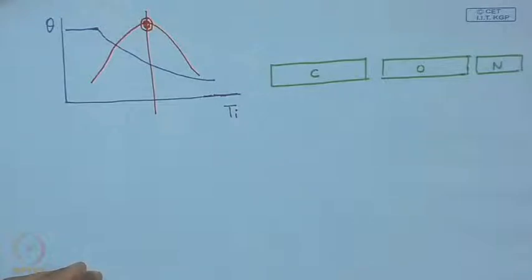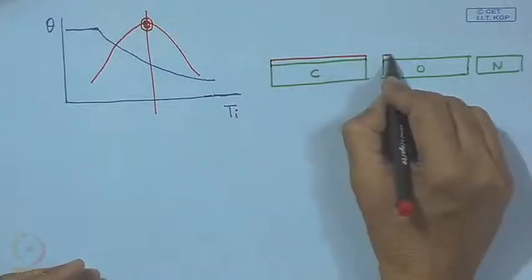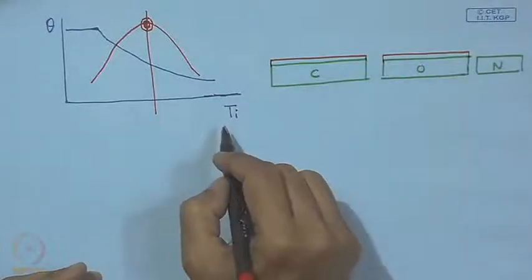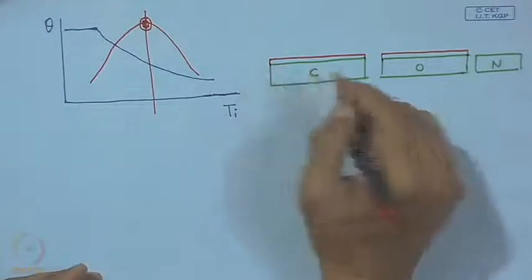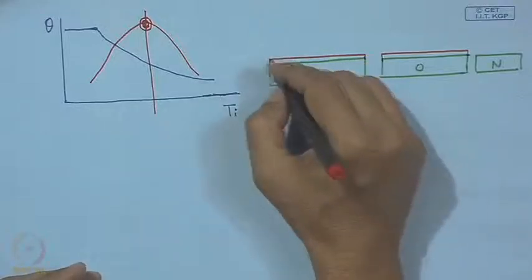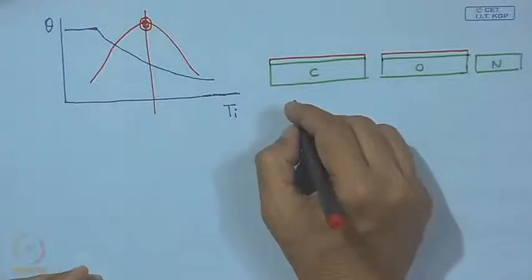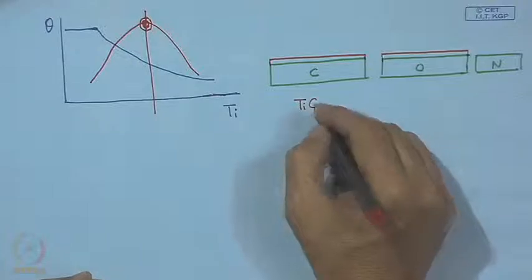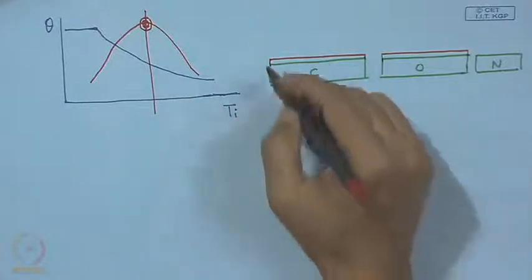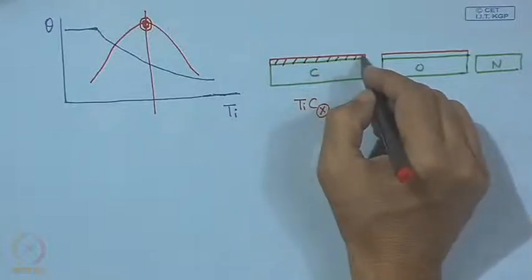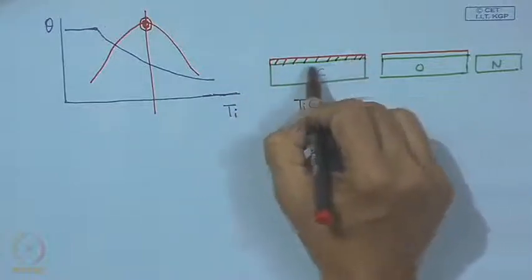Vigorous reaction means here, instead of a fine layer, it is the thickening of the reaction layer, and this thickening goes along with the amount of titanium. This increased amount of titanium actually thickens the layer and at the same time makes the outer surface richer in titanium. So, the outer surface which is richer in titanium, that means a very low value of x, gives a still further improved wetting, but that is at the cost of bonding. So, this thick reaction layer no longer supports any externally applied force, and the breakage occurs at this interface.